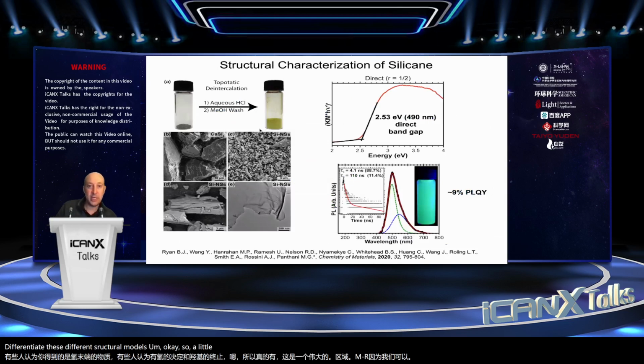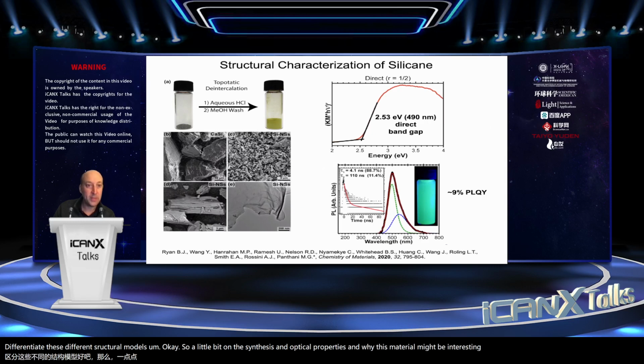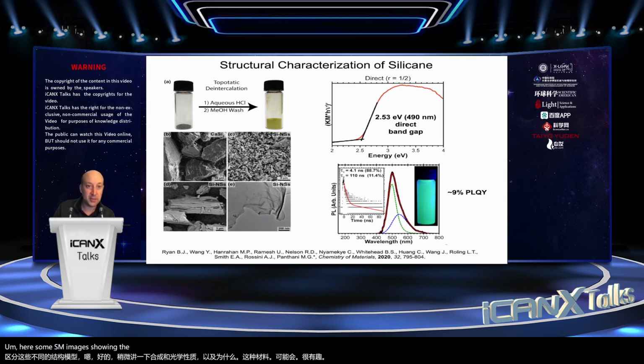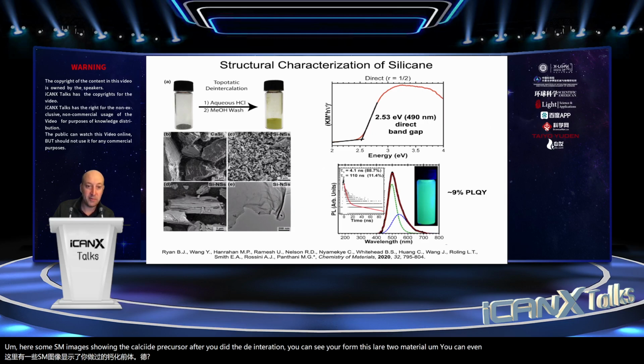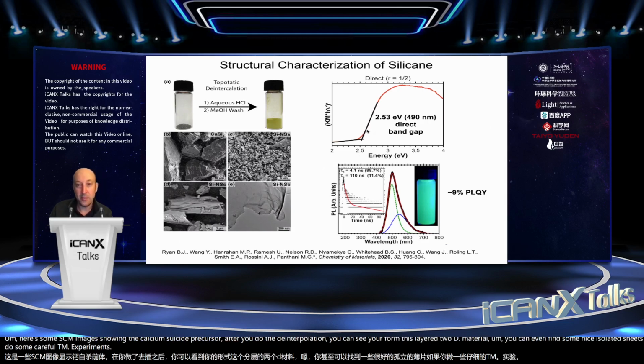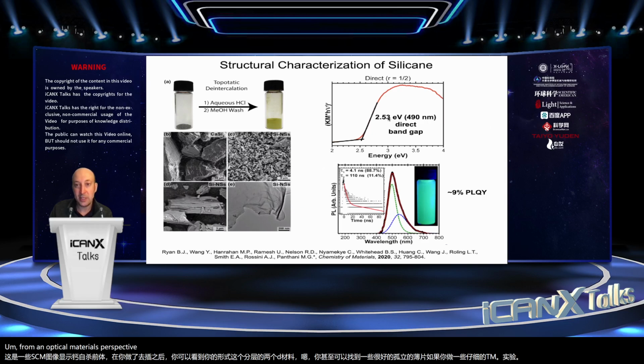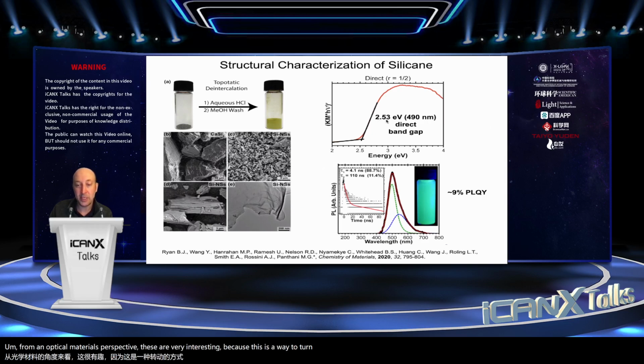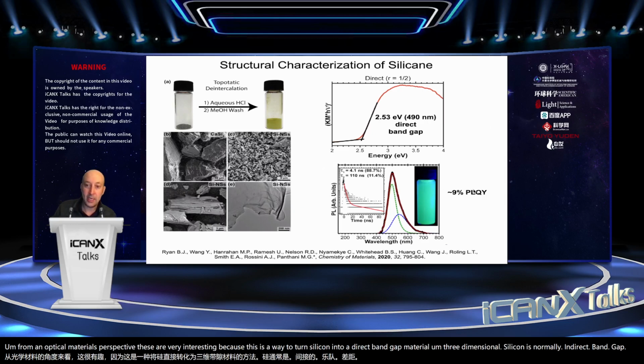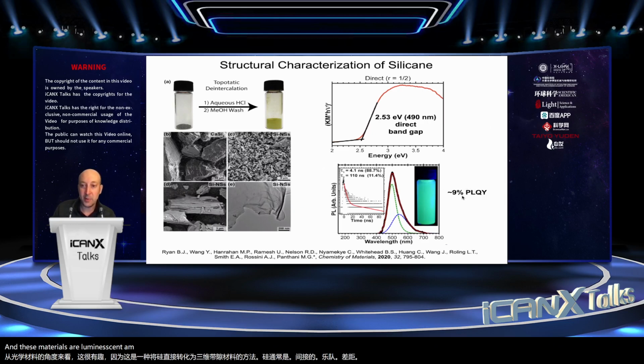Okay, so a little bit on the synthesis and optical properties and why this material might be interesting. Here's some SEM images showing the calcium silicide precursor. After you do the deintercalation, you can see you form this layered 2D material. You can even find some nice isolated sheets if you do some careful TEM experiments. From an optical materials perspective, these are very interesting because this is a way to turn silicon into a direct bandgap material. Three-dimensional silicon is normally indirect bandgap. And these materials are luminescent. They have about a 9% PLQY here.